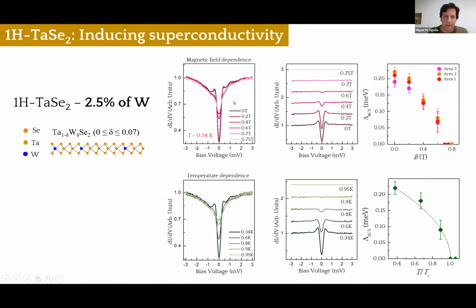Okay, so here I show you the spectroscopy for one of these samples. In this case, it's 2.5% of tungsten atoms, right? So this is the magnetic field dependence, and this is the temperature dependence. As before, we also see a dip at the Fermi level, centered around the Fermi level, with a width of about 0.5 milli-electron volt or so. But on this occasion, the dip responds to the magnetic field. If we increase the magnetic field, the width and the depth of this dip vary up to 0.75 Tesla, above which it basically remains constant. So if we normalize all these curves to the upper curve, where we observe no variation, a clear superconducting gap emerges here, right?